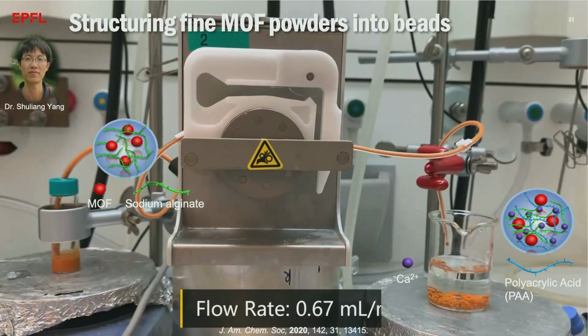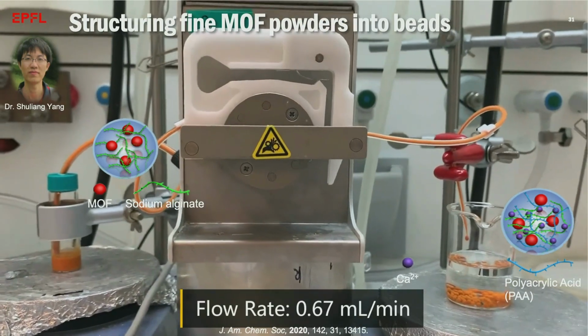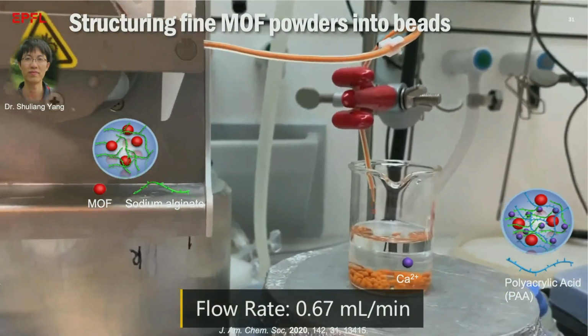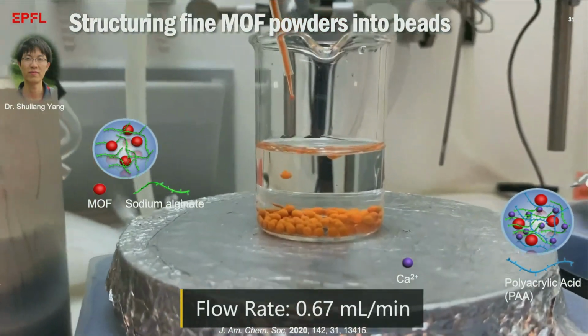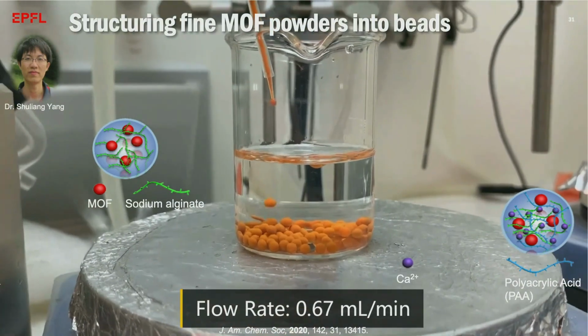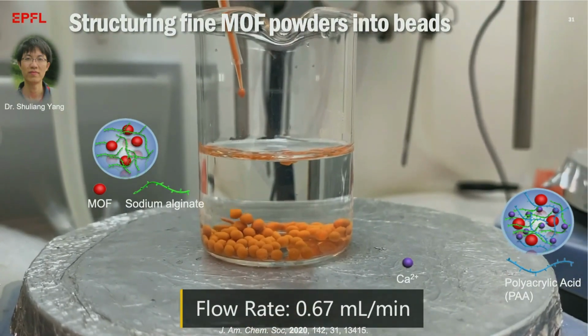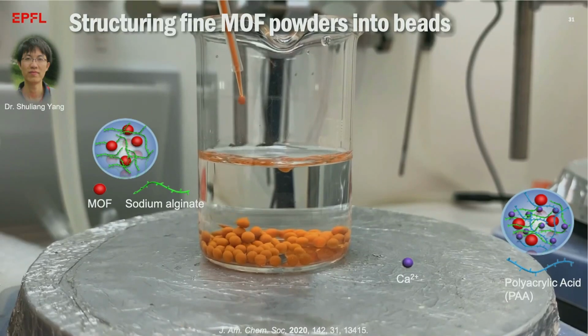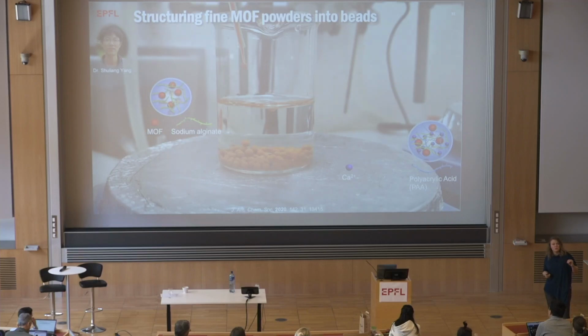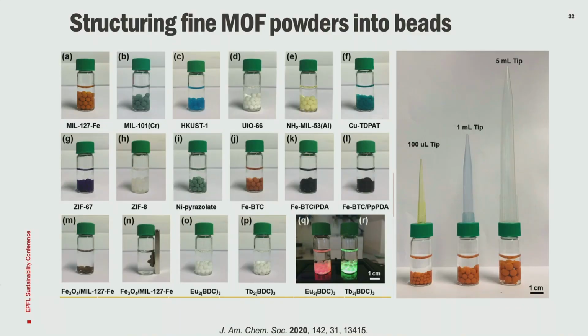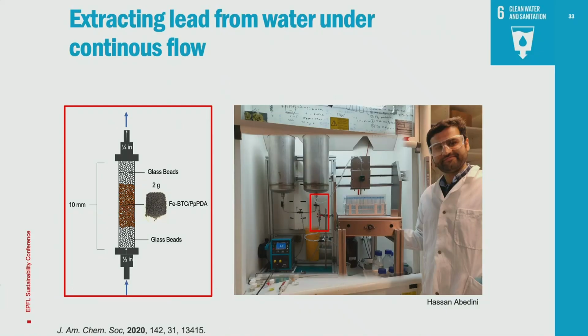We're also developing strategies so that we can structure these fine powders into beads. So this is done in water. On the left, you had sodium alginate with the MOF. Here you can see the MOF in the sodium alginate solution. It basically forms a polymer as it hits the solution, which we're forming these nice beads. And the reason that we need to do that is because we want to study these materials under continuous flow, okay? In continuous flow, powders are actually really difficult to work with because we get huge pressure issues across our columns. Also, the fine powders are really difficult to handle, so this is why we're doing this.